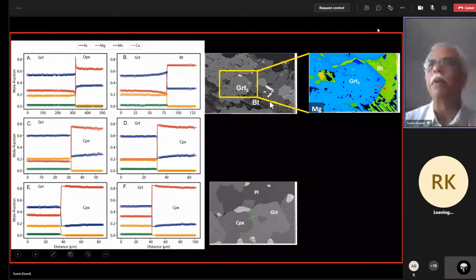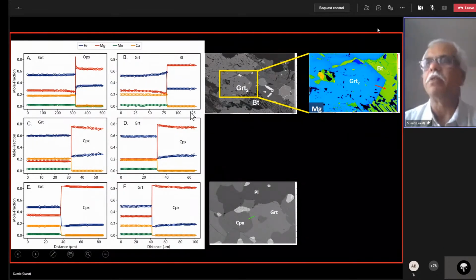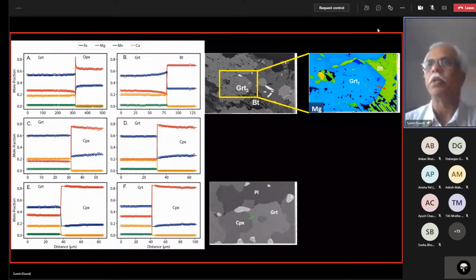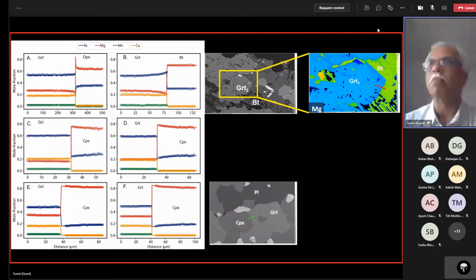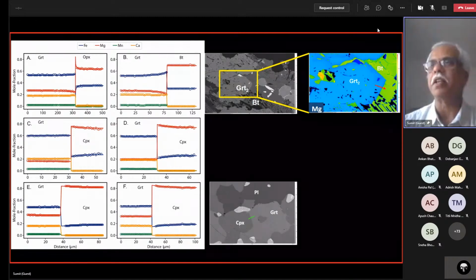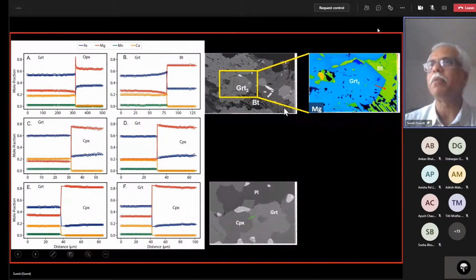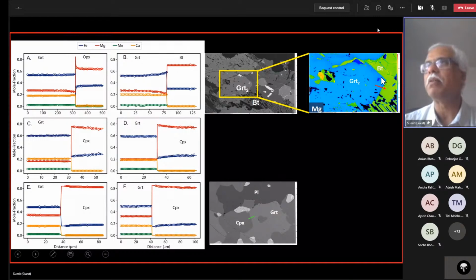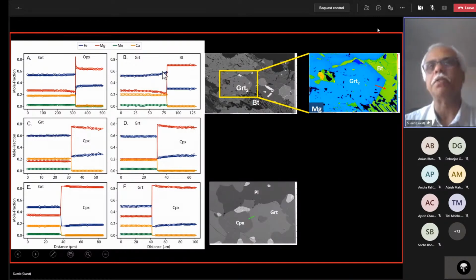And you see that in this right image here, where you have an element concentration map. The colors show you how much magnesium is in these particular places. The brighter the color, the more towards red or lighter colored, the higher the concentration of magnesium. The lower the magnesium concentration, the darker the colors. And what you see immediately in the garnet is it's pretty much the same composition, this blue color everywhere, except when you go really close to the biotite, there's sort of a dark blue rim that forms here. And that is where you measure these concentration profiles.